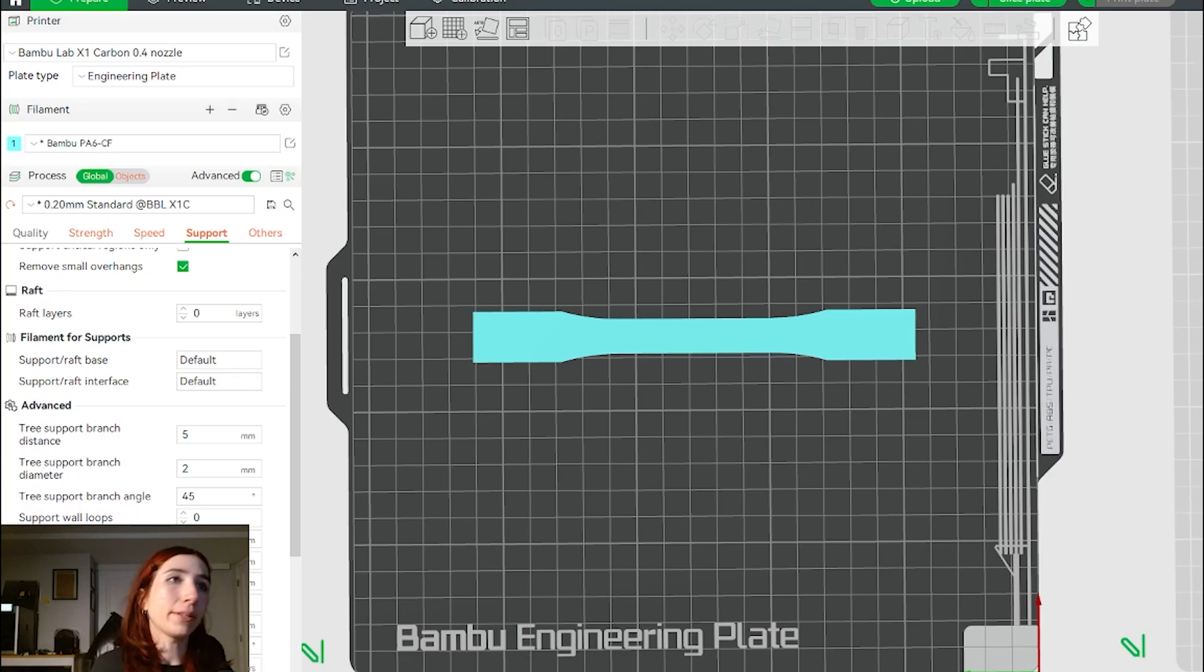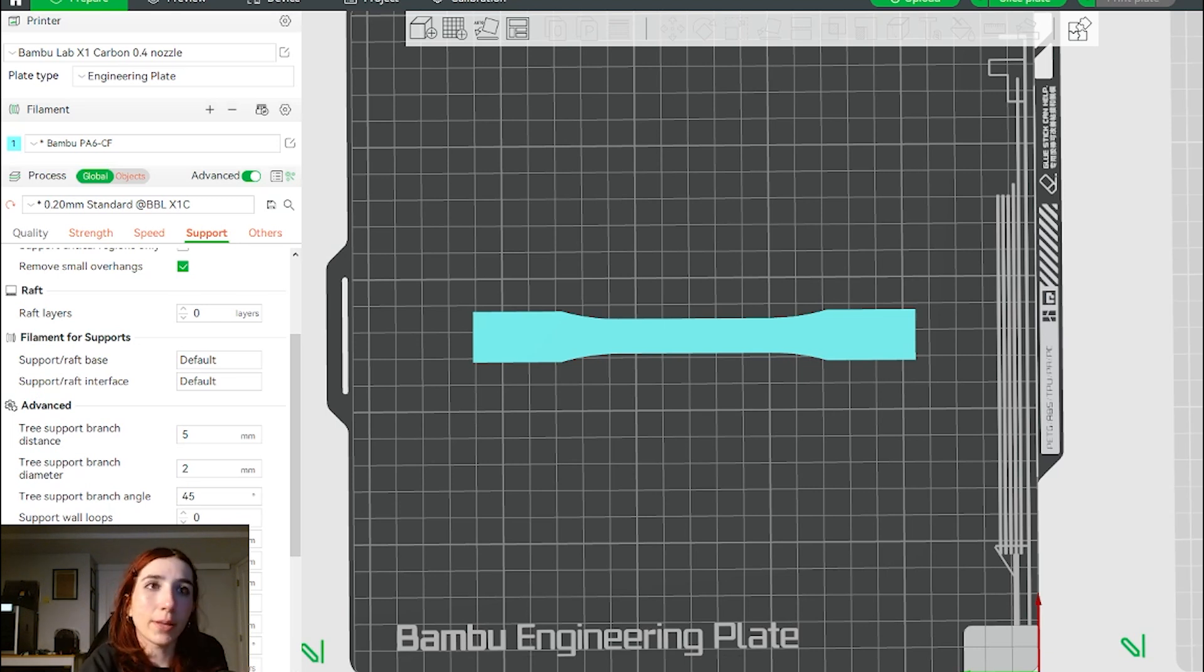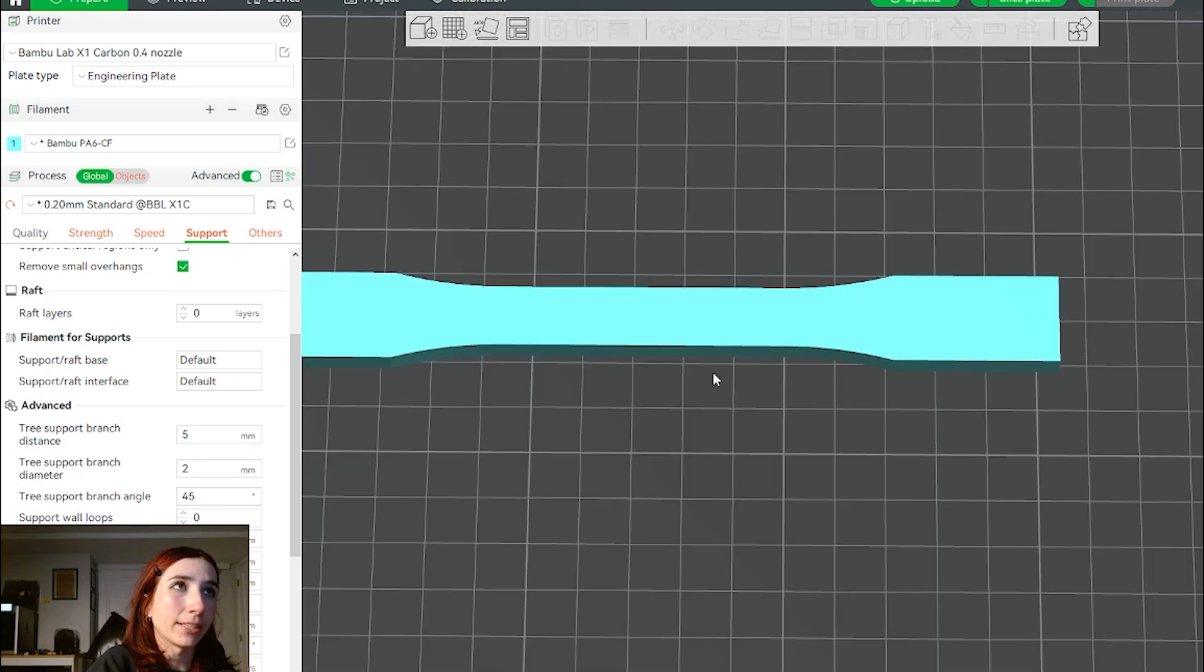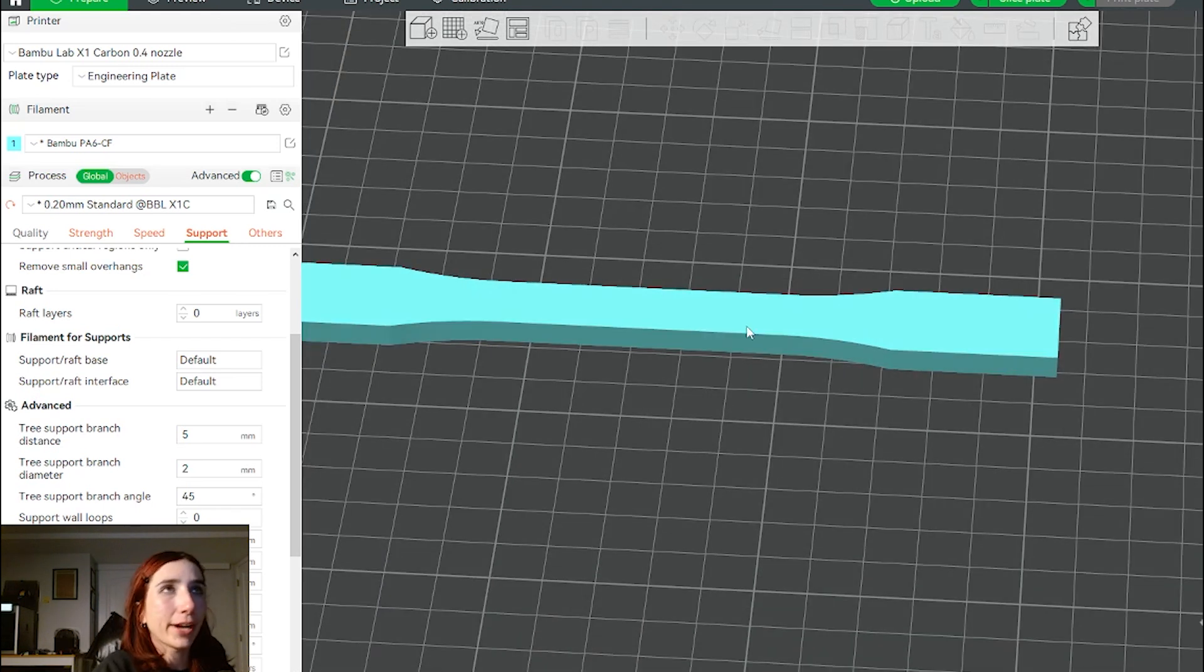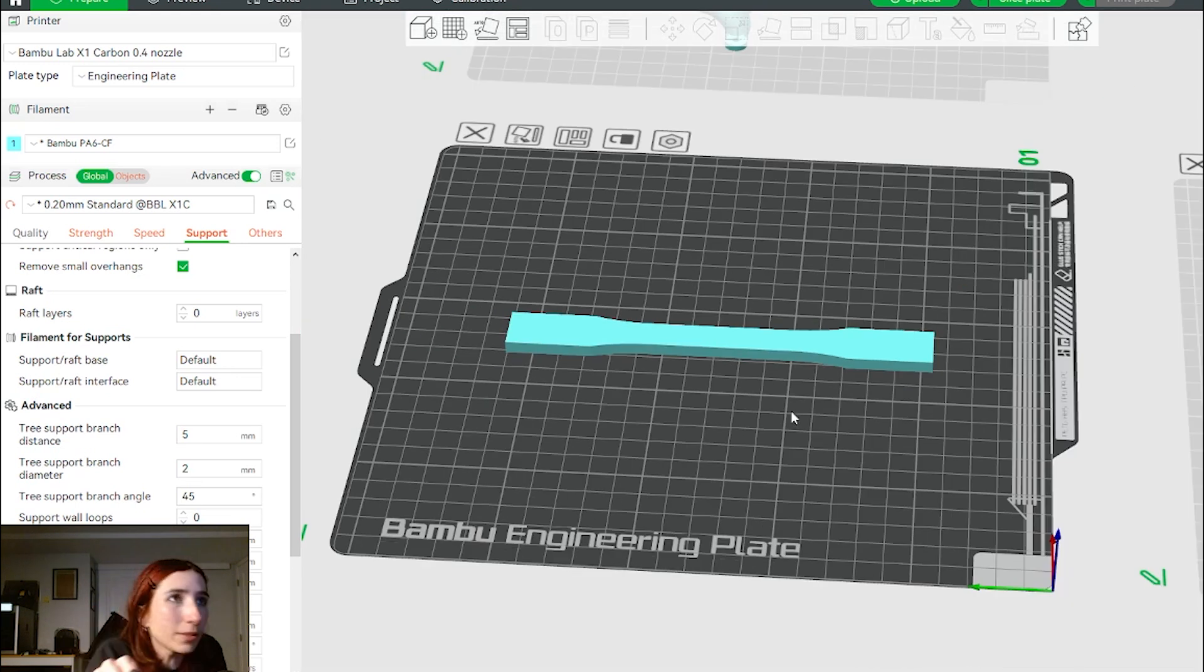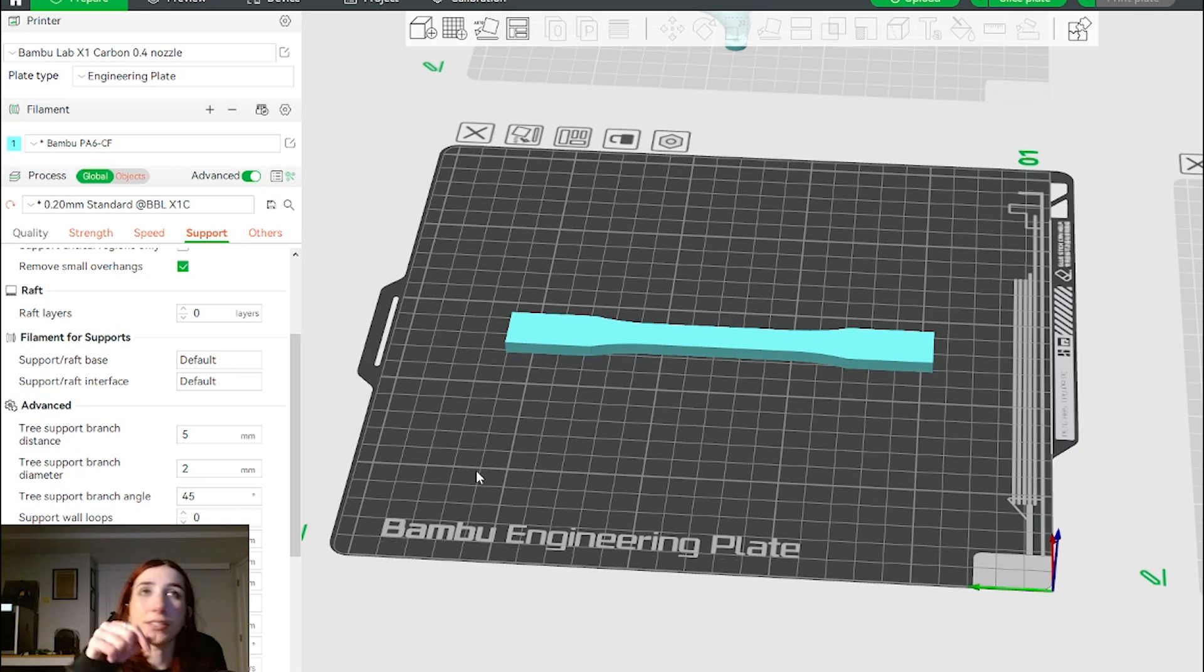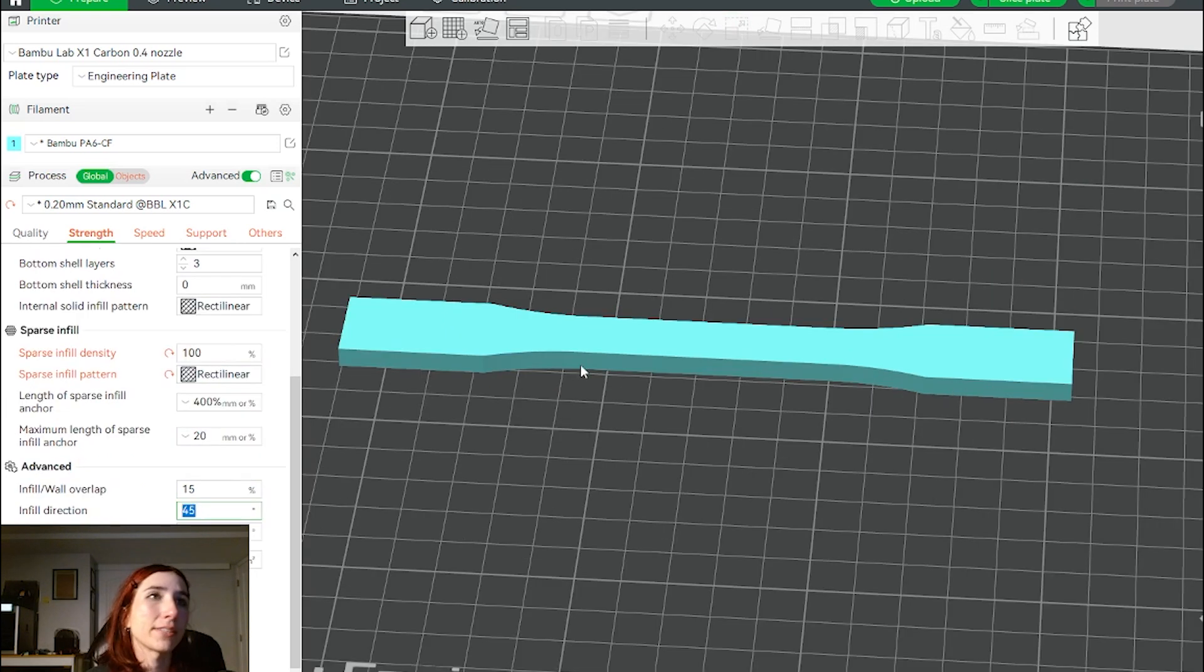Okay so now that we're in a slicer, let me emphasize on what I mean. So those samples you saw in the intro clips were tensile dog bones that look like this. They have a five millimeter height. They're printed flat on the build plate and the raster angle was something I was varying to see how it would affect the strength of the part coupled with the print orientation.